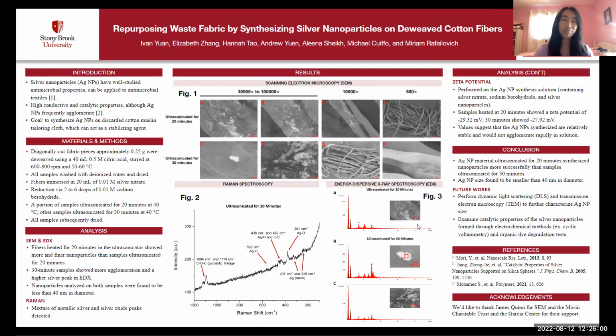We used approximately 0.24 grams of fibers that were deweaved with citric acid and washed. We immersed these in a 20 milliliter solution of 0.01 molar silver nitrate and reduced the silver nitrate with 2 to 6 drops of 0.01 molar sodium borohydride. Then we ultrasonicated these samples at 40 degrees Celsius for 20 or 30 minutes and dried them. We imaged the nanoparticles with SEM as shown in figure 1. Energy dispersive X-ray analysis, or EDX, was simultaneously performed to verify the existence of silver, as shown in figure 3.